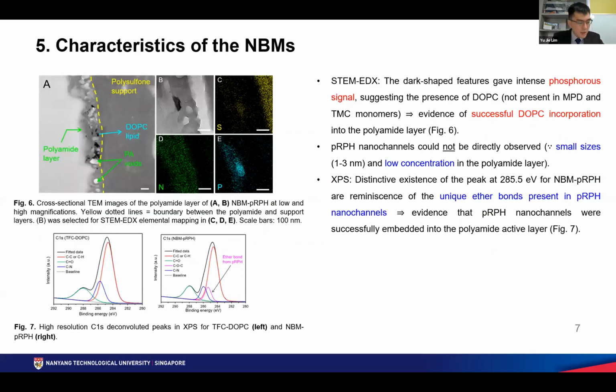Now, let us take a look at section 5, the characteristics of the NBMs. First, we use scanning transmission electron microscopy, STEM, to observe the morphology of the NBMs. It was revealed that there were some odd-shaped features in the polyamide selective layer, and through EDX analysis, it was proven that these features actually gave enhanced phosphorus signal, suggesting the presence of DOPC liposomes inside the membrane selective layer, because the phosphorus element is not present in MPD or TMC monomers used in interfacial polymerization.